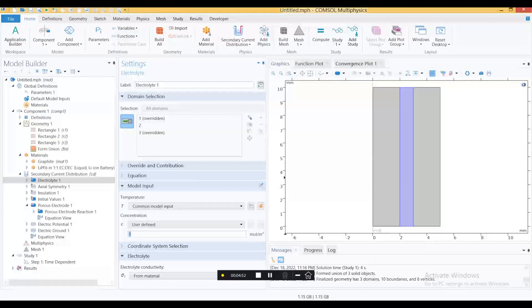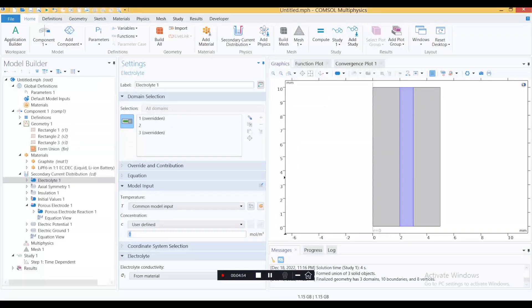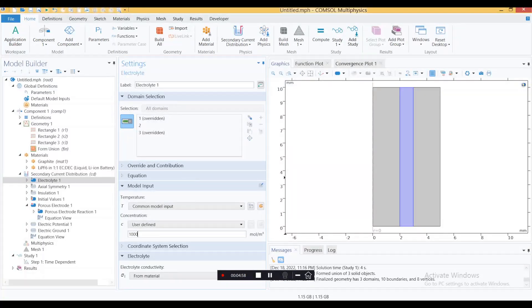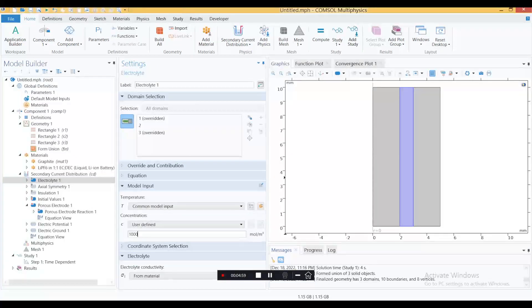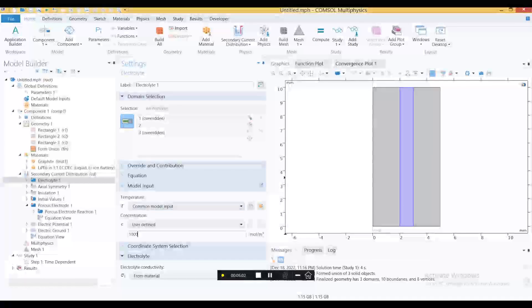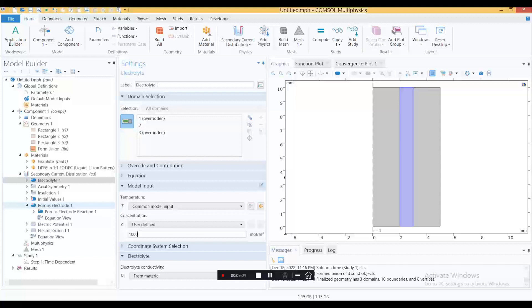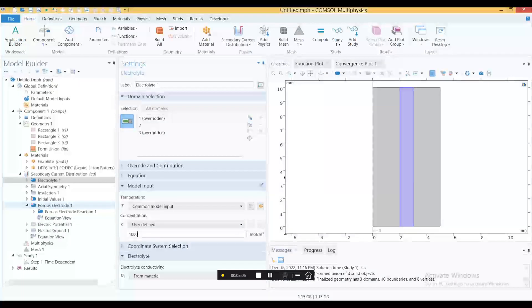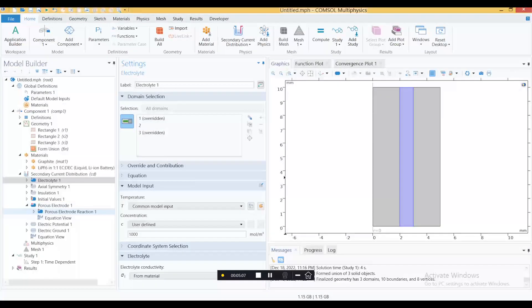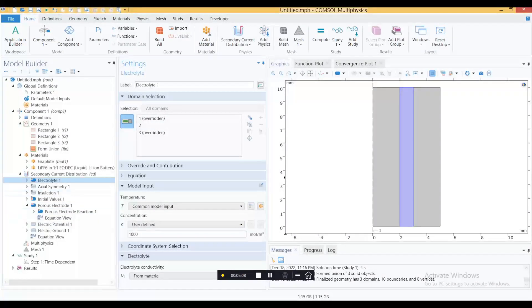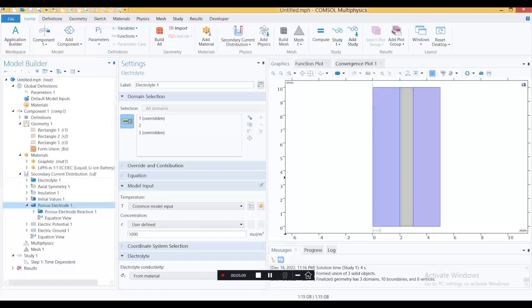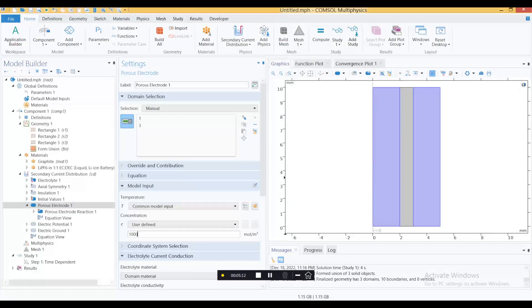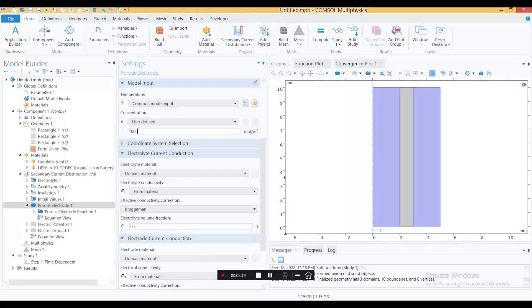After that, go to the electrolyte. This concentration is basically your initial concentration of your electrolyte. Most of the simulations or research papers will specify this to be 1000 for supercapacitors. For batteries it varies. Keep it 1000 here as well. That's mole per meter cubed.